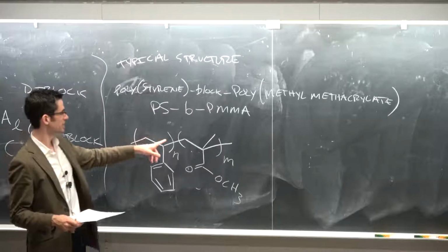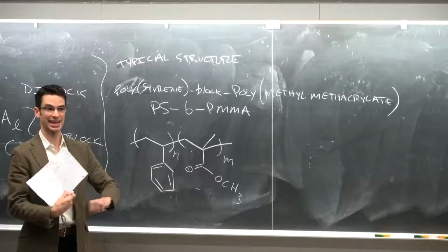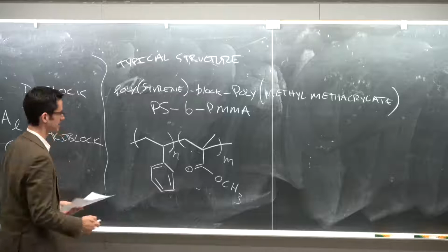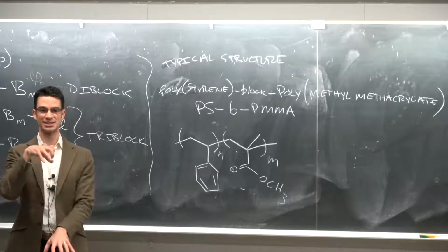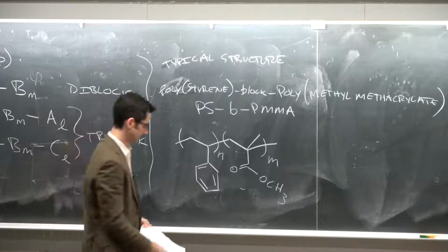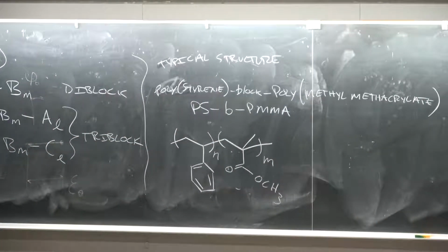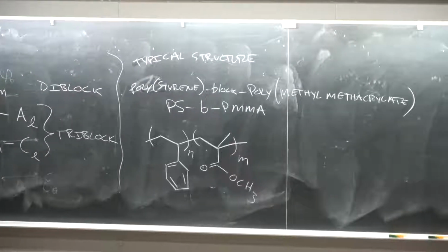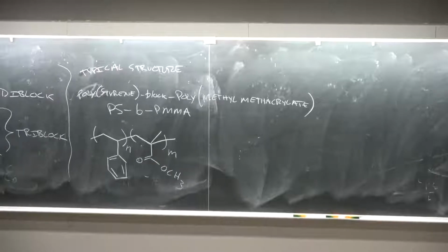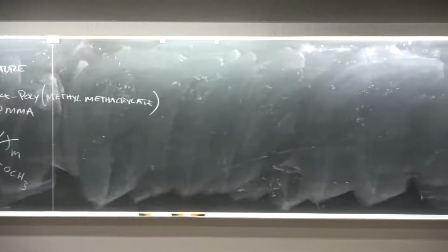So these ordinarily do not want to mix, but they're tied together covalently. They can't escape from each other. So instead of forming two phases like salad dressing, they form these very characteristic microstructures. Again, they're actually characterized by nanoscale domains, but because it was already called micro from the early days of polymer science, those are the names we have.